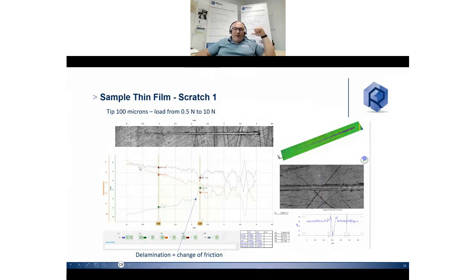During the scratch, we are monitoring the progressive load, the friction, and the penetration depth and residual depth. When you increase your friction, you change layer, and when you change layer, you directly acquire the LC, the critical load. You know the load: the first one was 3 Newton, the second one was 6 Newton, and you see directly the residual imprint with a confocal image because we record with our 3D imaging.